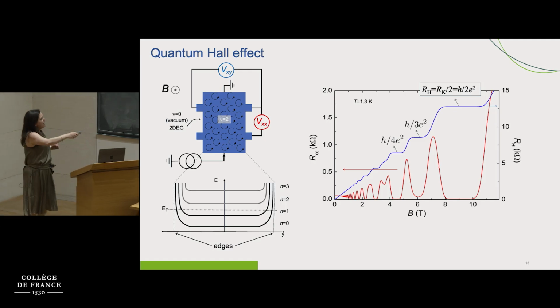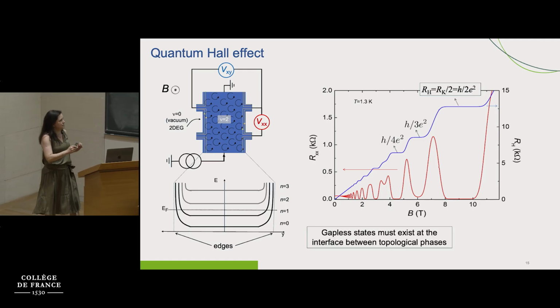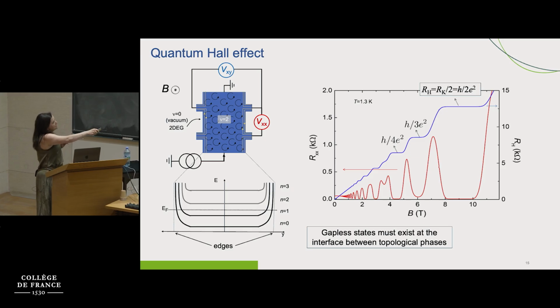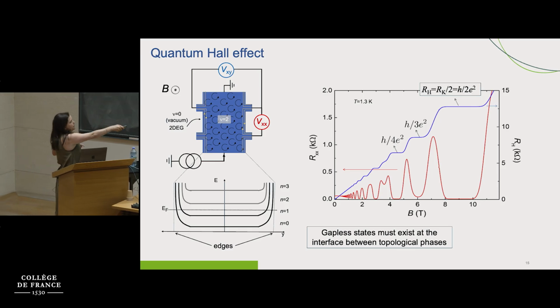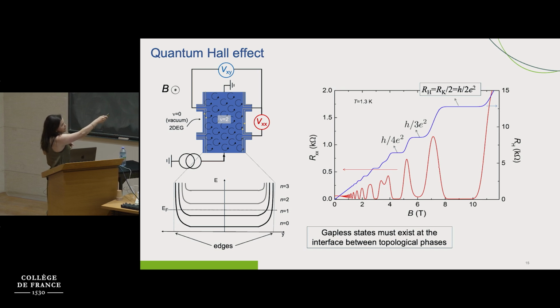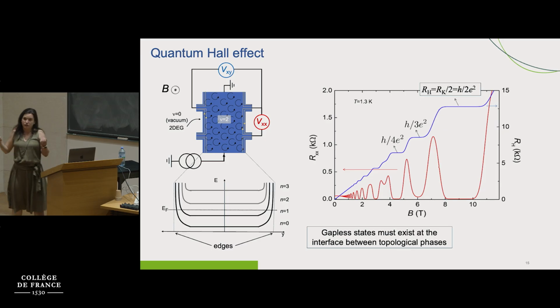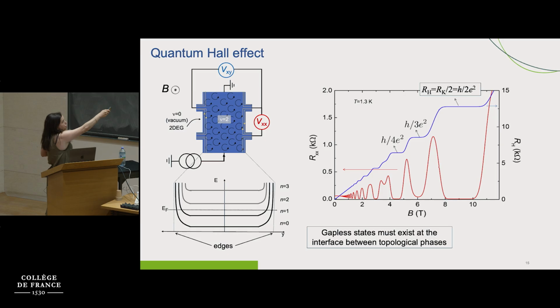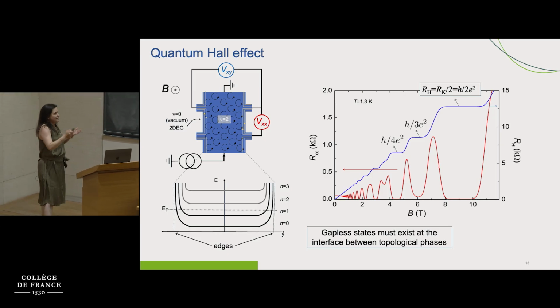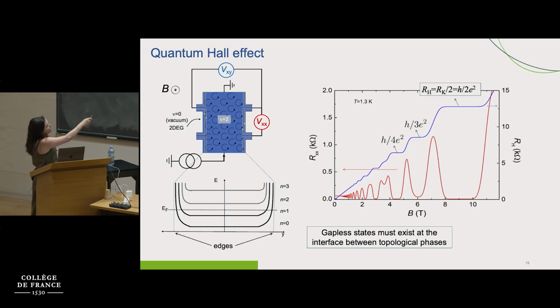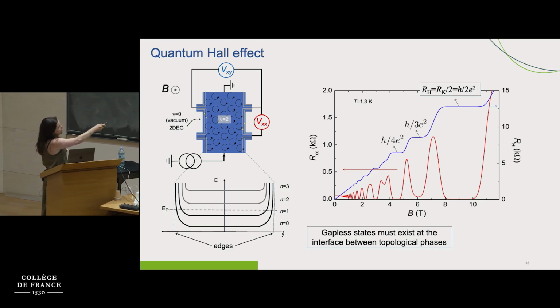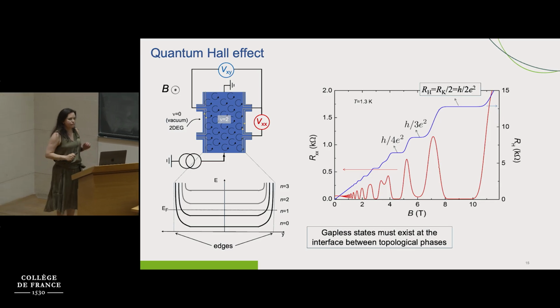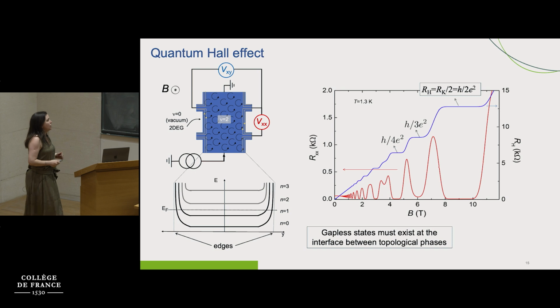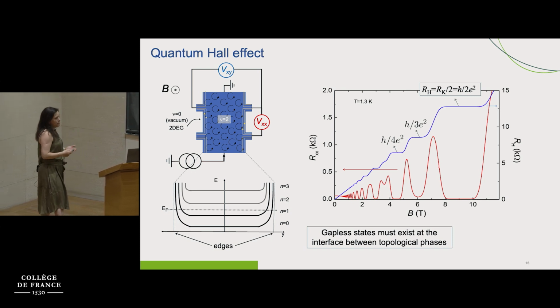So now, if we look at what happens on the edges, because we know that gapless states must exist in the interface between two topological phases, we're going to see that we have dispersive modes. These dispersive modes are going to be responsible for two things. The first one, the drop to zero of the longitudinal resistance, because now the conduction between this electrode and this electrode is a perfect conduction, because we cannot backscatter from this edge to the other edge of the sample. This is exactly the same as Antoine just said before. And now we are going to have a voltage drop between the two sides of the sample, which is also quantized. So, okay, this is the integer quantum Hall effect. We already know this. This is the experimental characteristic of the integer quantum Hall effect.